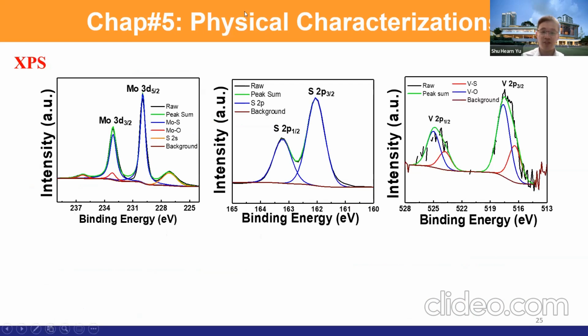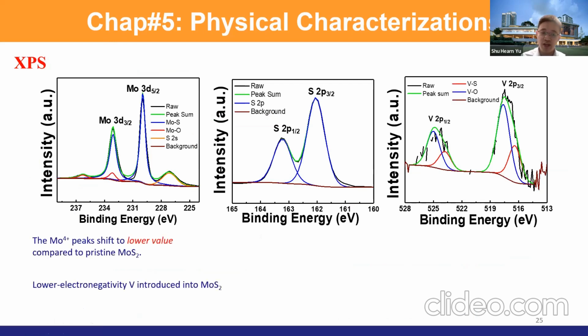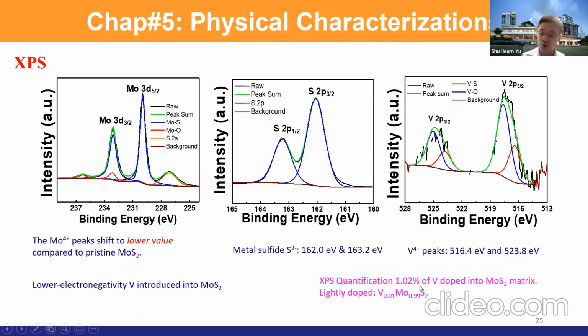And this is the XPS result. We're trying to quantify the doping level of MoS2. So we find that the doping level of MoS2 is about 1.02%. So there's about 1.02% of vanadium doped into MoS2 characterized by XPS. XPS is more surface sensitive, so I believe this result will be more important for electrocatalysis, because electrocatalysis is also an interface behavior.